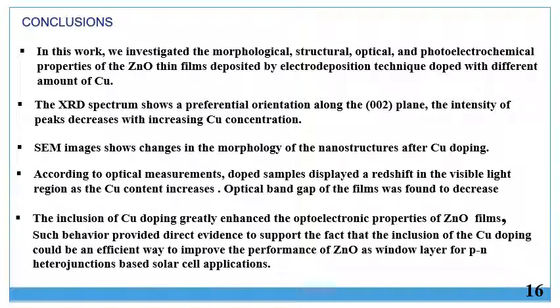According to the optical measurements, doped samples displayed a redshift in the visible light region as the copper content increases. The optical band gap of the films was found to decrease. The inclusion of copper doping greatly enhanced the optoelectronic properties of zinc oxide films. Such behavior provided direct evidence to support the fact that the inclusion of copper doping could be an efficient way to improve the performance of zinc oxide as a window layer for p-n heterojunction-based solar cell applications.